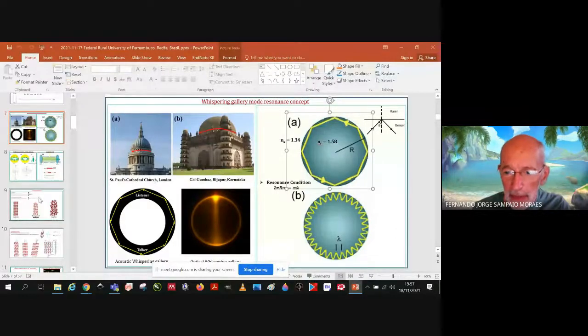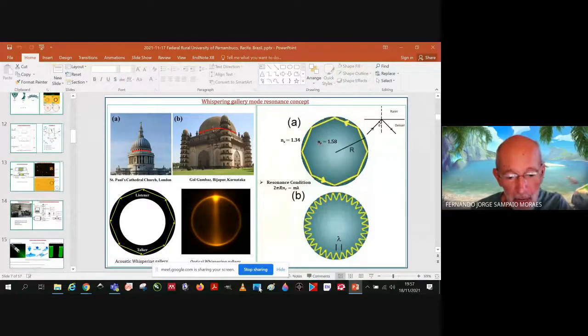For this whispering gallery mode optical resonance to occur, those peaks to occur, the condition of having the refractive index higher than the surrounding medium has to be obeyed. But when we go to the isotropic phase temperature or near this transition, what we observe is loss of refractive index contrast, and this results in the peaks nearly vanishing. So we no more see those peaks. However, we definitely see those peaks, but very weakly, in the case of bigger droplets. Oh, I see. So you don't lose the resonance completely. Yeah, exactly. Okay.